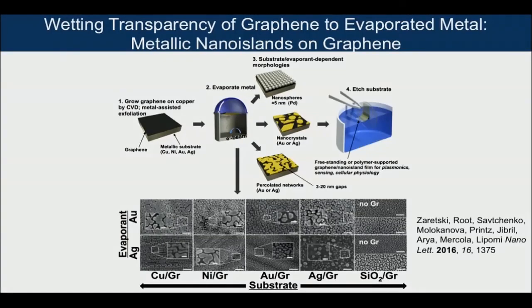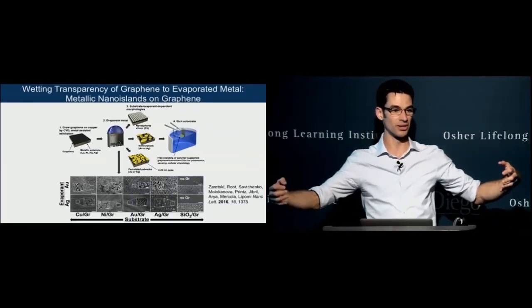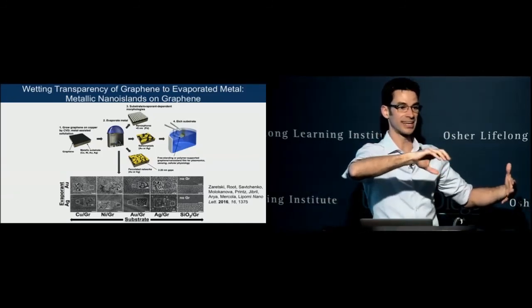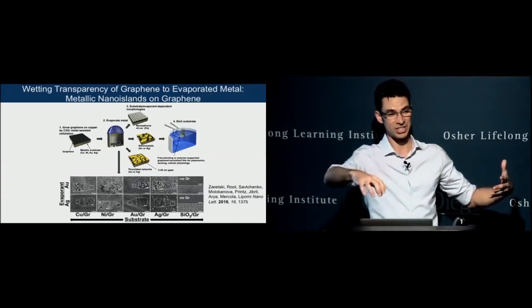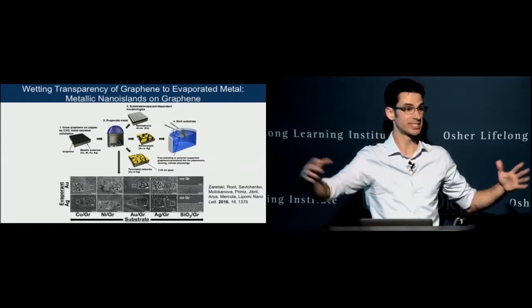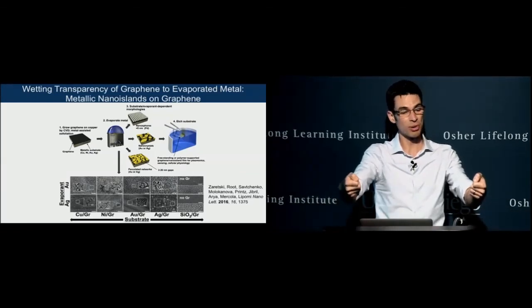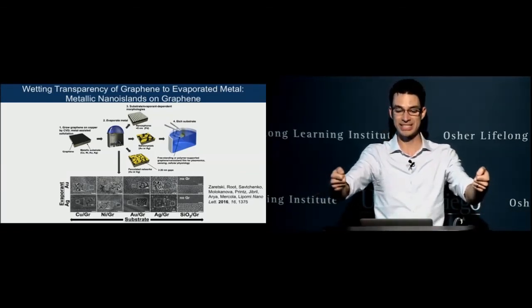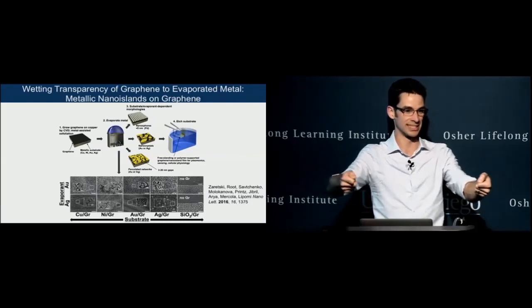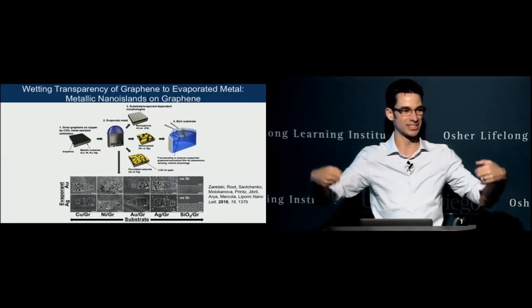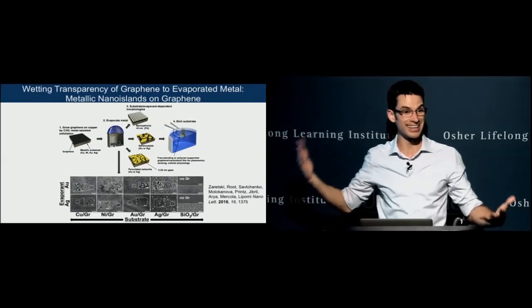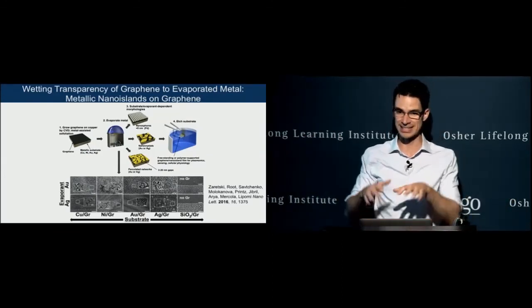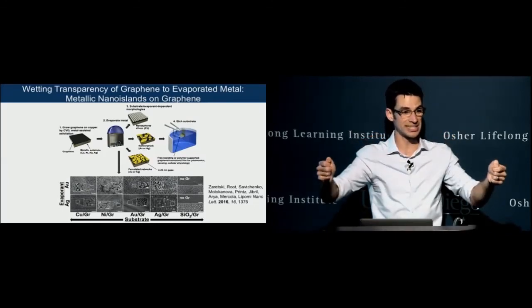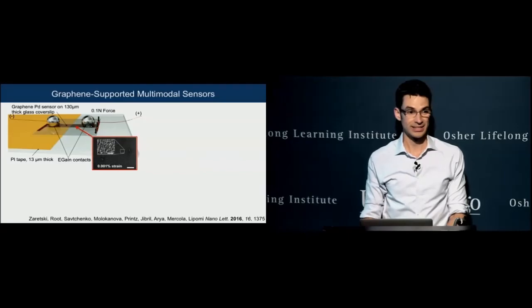Now, what's interesting about having particles that are closely spaced is that the conductivity between these little metallic islands is mediated by something called tunneling, where an electron can end up on an adjacent metal nanoparticle without us doing much of anything. But the tunneling probability changes exponentially based on the amount of stretching that these things undergo. So you can see my interest in thin things and stretchable things is leading me to an idea here. What if we could make a sensor based on these graphene and nanoparticle films that was very sensitive to stretching? It turns out we can do that.